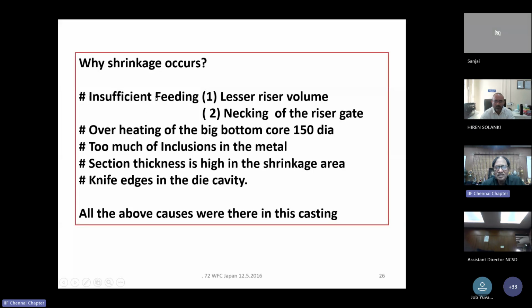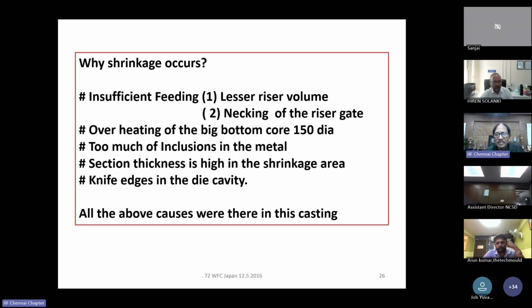General reasons: insufficient feeding, lesser riser volume. Necking of the riser is also causing insufficient feeding. Overheating of the big bottom core also makes the metal remain hotter for a long time and gives rise to shrinkage areas. Too many inclusions in the molten alloy can also cause shrinkages. Section thickness being high also causes shrinkage areas. Knife edges in the die can also cause local shrinkages. All the above are the general causes for shrinkage voids to occur.